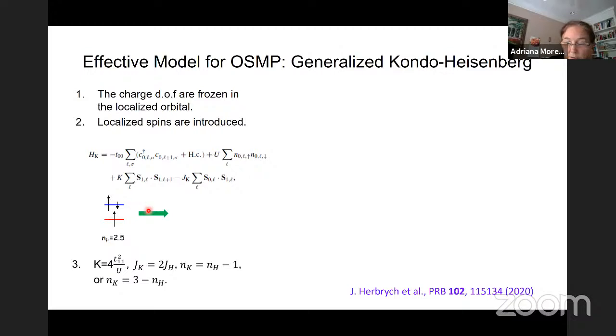So in order to go to the Kondo model, we say we have the localized spin here, and we have to put 1.5 electrons in the metallic orbital. And due to the particle-hole symmetry of the Kondo model, this is going to be equivalent to the same result we obtain if we put 0.5 electron in the metallic orbital.